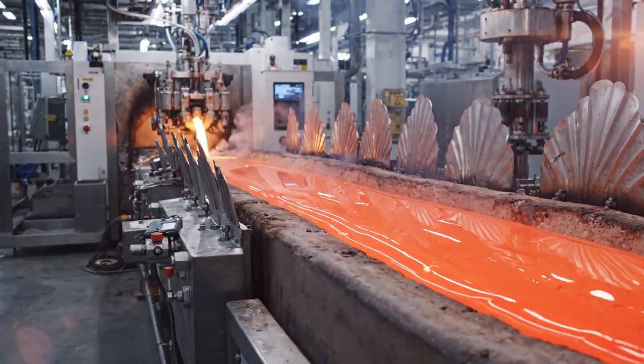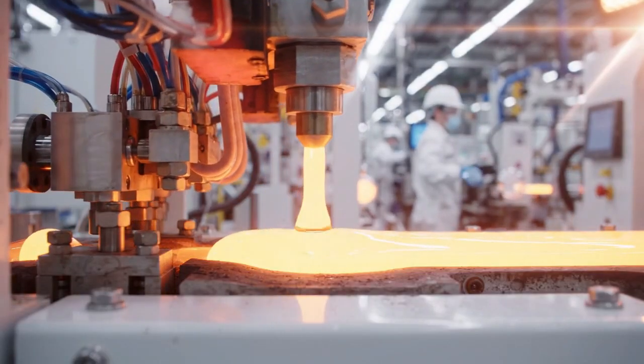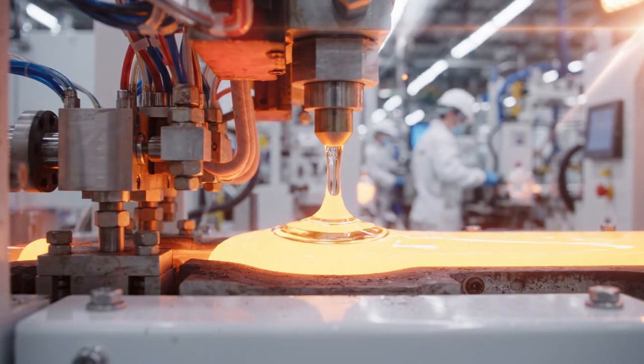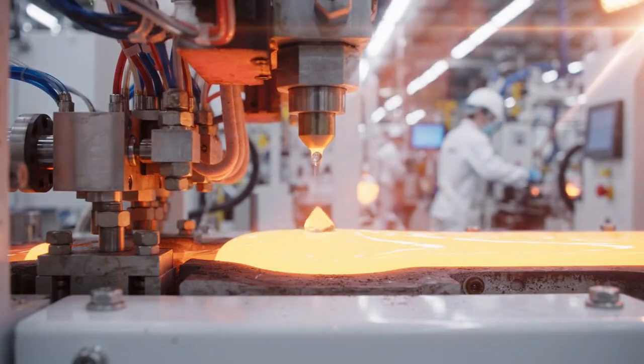The conditioning zone cools the glass uniformly from melting temperature to the precise working temperature needed by the forming machines. Hearth temperature control adjusts glass viscosity with precision of plus or minus 2 degrees across the entire width, ensuring uniform gob weights.